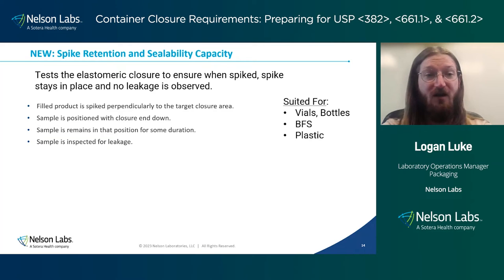So if you look, it's a pretty simple method where you spike the product perpendicular to the closure, you put that closure end down, and then the sample will just remain in that position for what's typically the intended dosage duration. And then the sample is inspected for leakage.